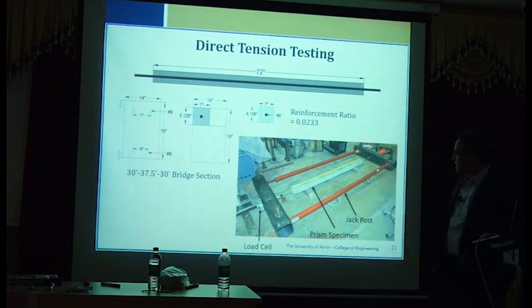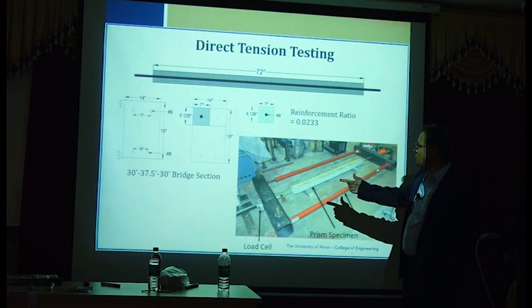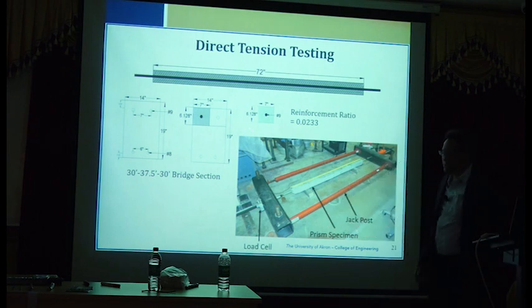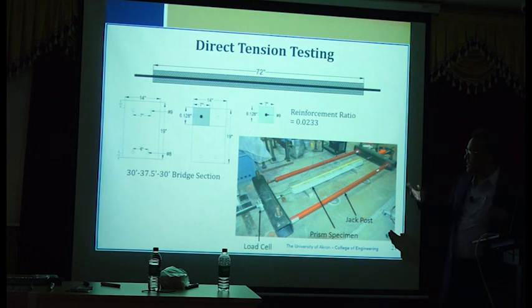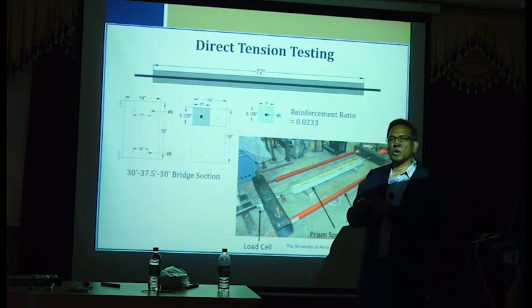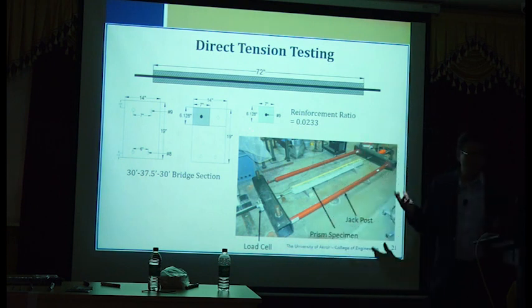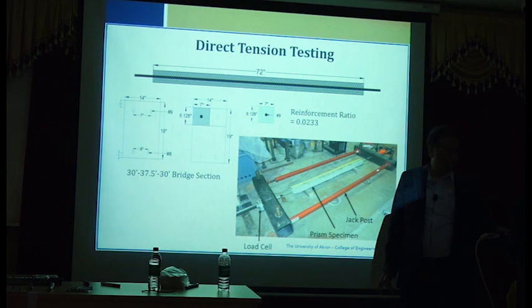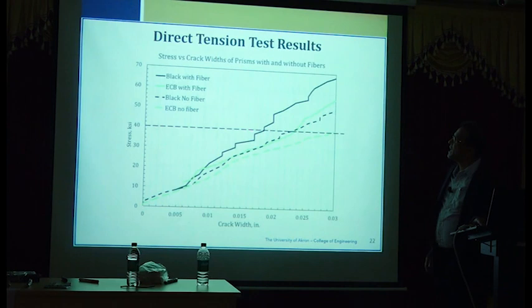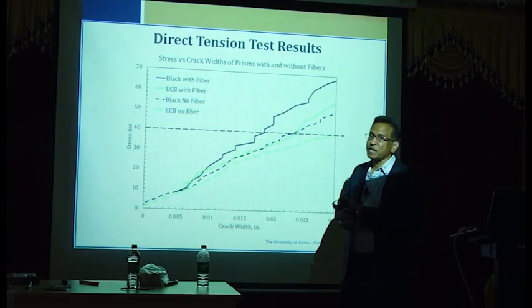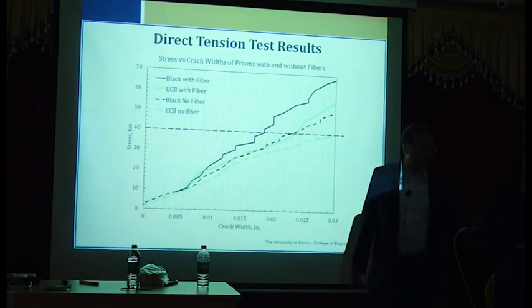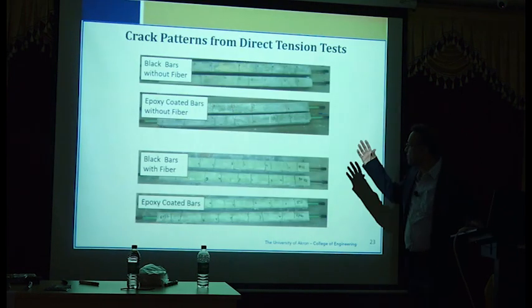So in that we used prism tests. Prism tests, we had again applied load in a horizontal frame, and then we looked at the crack widths for different types of corrosion resistant bars, with and without fiber. So we have lots and lots of test data. Of course, Srikant also did a lot of theoretical work, and he tried to correlate theoretical predictions with the actual test results. So once again, without going into the details, fiber did help a lot in terms of crack width and crack propagation. So these are some of the failed prisms.